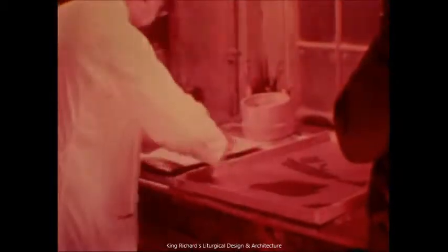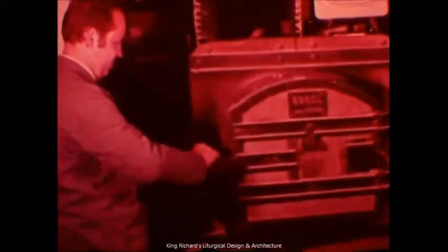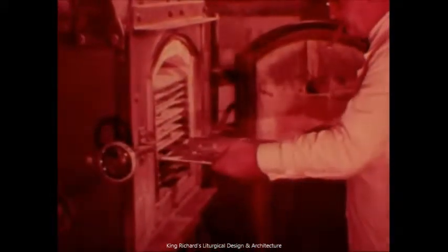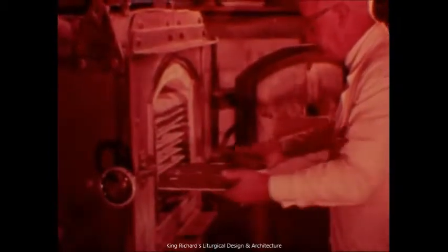We're ready to fire. On an asbestos tray, the pieces are placed paint side up. Fusion of glass and paint occurs at about 600 degrees centigrade or 1100 degrees Fahrenheit. In a preheated gas or electric kiln, it takes roughly 10 minutes to fire the glass. Not hot enough or long enough to melt the glass, but hot enough to vitrify the paint. When a slight sheen occurs on the glass, the paint has melted and fusion has taken place.